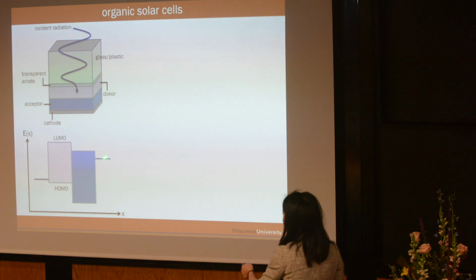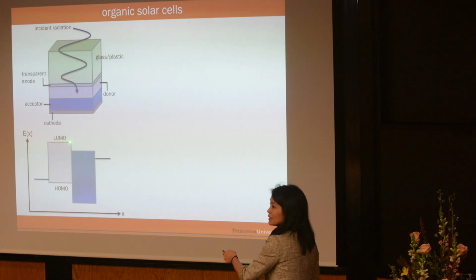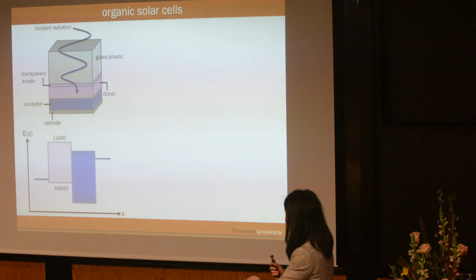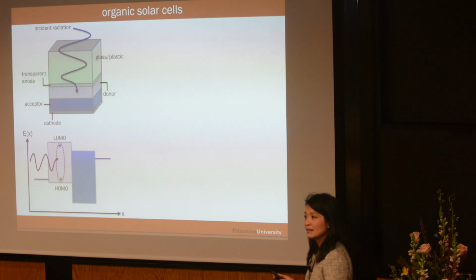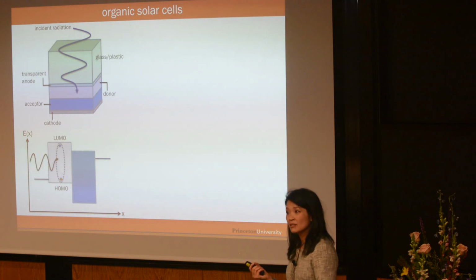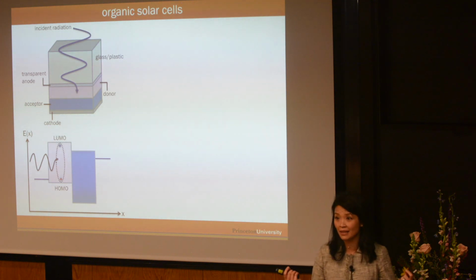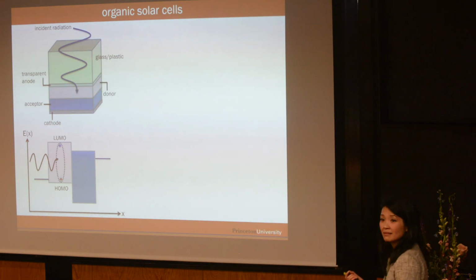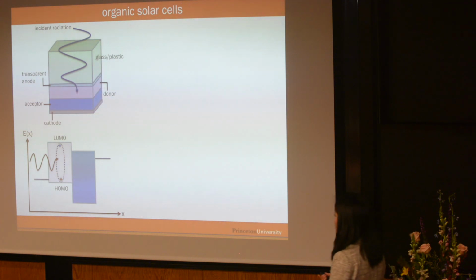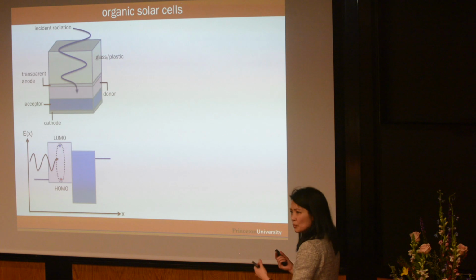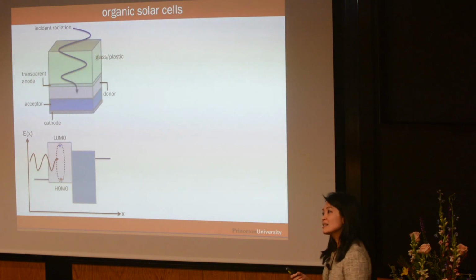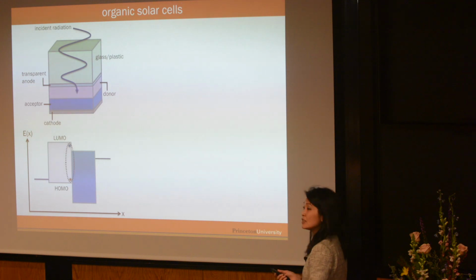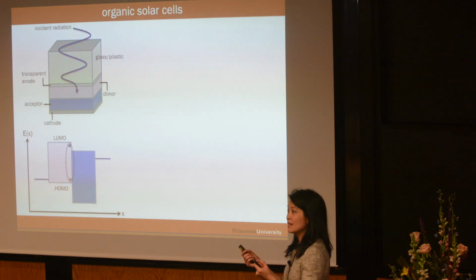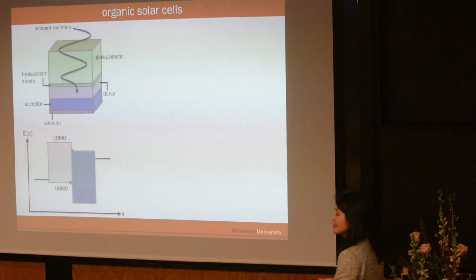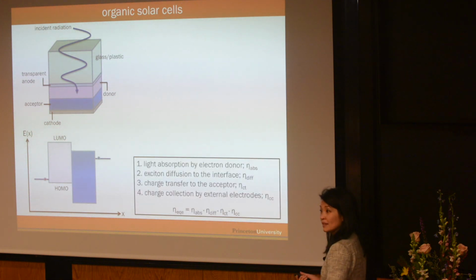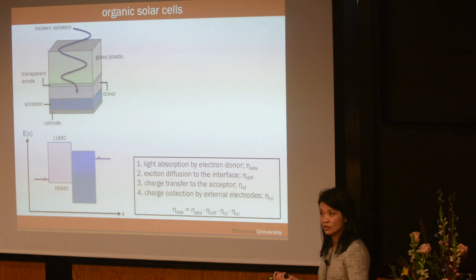And so these are the work functions of the electrodes, and the lowest unoccupied molecular orbital and highest occupied molecular orbital of the donor and the acceptor. So when you shine light, these are low dielectric constant materials, so you don't generate free carriers automatically like in silicon. What you generate is an exciton. This is a tightly bound electron-hole pair. And that's generated in either phase, more commonly in the donor phase. And then this exciton needs to diffuse around until it finds an interface where there's sufficient driving force to split the exciton into free carriers. Once it splits, now you have free carriers, and you can collect them at the external electrodes. Okay? That's how the solar cell works.